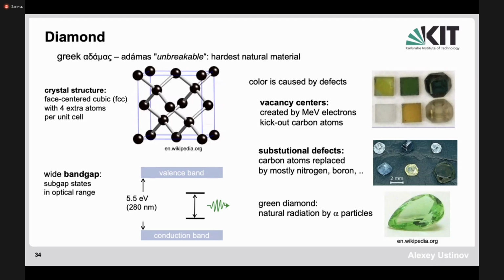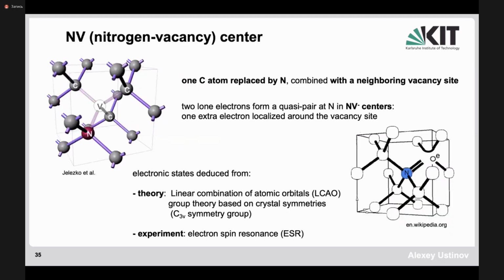For us, it's important that the diamond has a really very large band gap, a factor of 5 or more larger than a semiconductor, so it's really a very good insulator. And if there are states inside this gap from some impurities, the states can be manipulated by light. So one of the typical defects which occur in diamond is the so-called NV center. NV is an abbreviation which stands for nitrogen vacancy center.